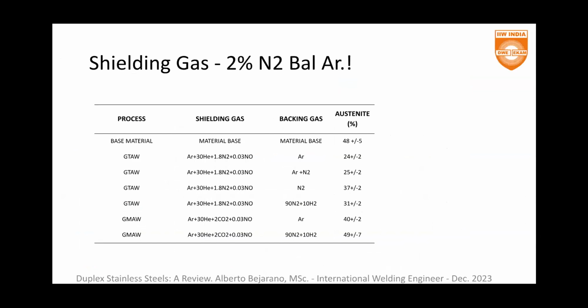Okay. Let's talk a little about shielding gas. Of course, the shielding gas is related with GTAW, with tungsten inert gas. But of course, we have flux core shielded, and we have GMAW. Normally, when GMAW, it's pretty common to use 80% argon, 20% CO2. That's all. The magic is done through the alloying elements.